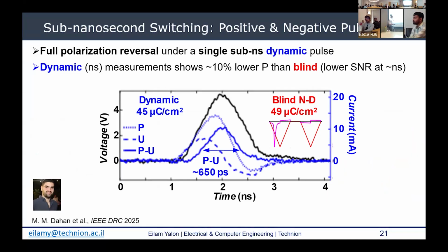Here we see, in black, the voltage across the capacitor. This is not the voltage that we applied from the pulse generator. It's the actual voltage on the pad, which we measure with an active probe, because there are some reflections and some of the power is dissipated across series resistance and so on. The dotted line is the current from the first pulse, which includes the polarization and charging and discharging. The dashed line is the current from the second pulse, the up pulse, which only includes the charging and discharging of the capacitor. And the solid blue line is the difference between the two, which is the net polarization.